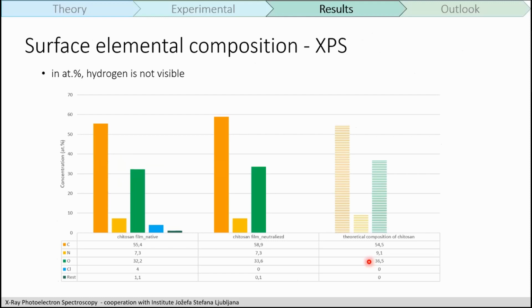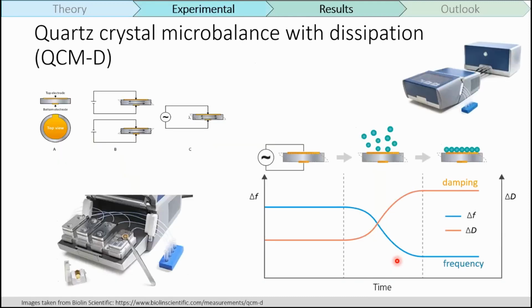The surface elemental composition was also calculated and measured, and the results were rather similar, once again proving that the chitosan was actually on the surface.